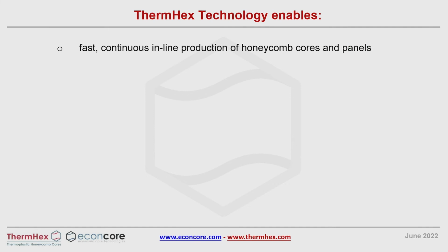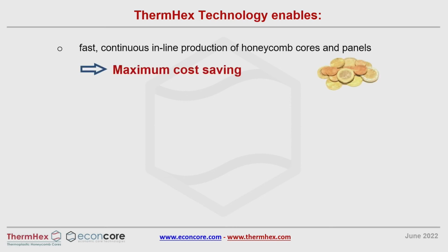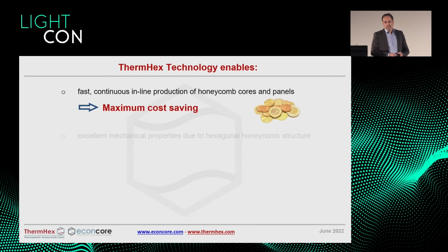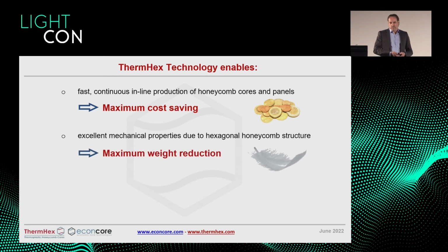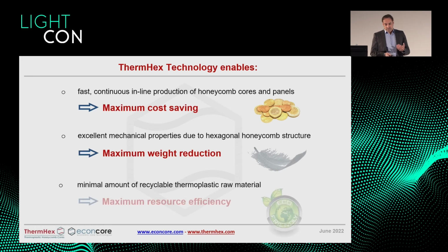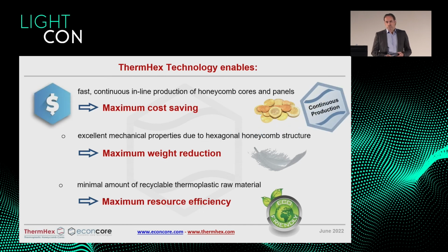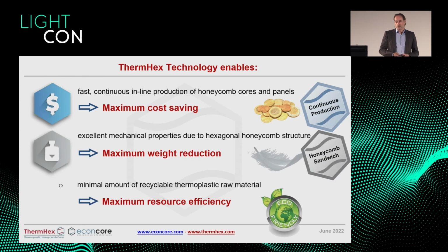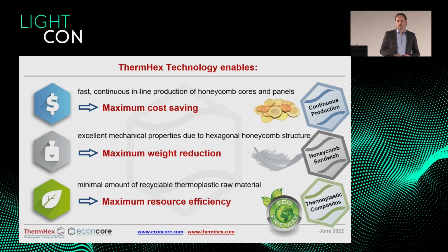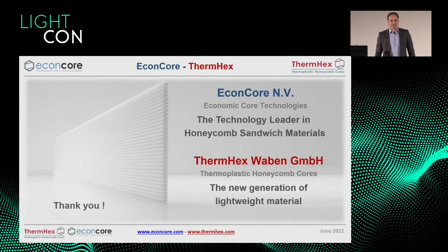So this brings me to the conclusion that we have with our process a fast inline production process for the cores and the panels, which allows maximum cost saving. We have the excellent mechanical properties of a hexagonal honeycomb structure, which allows maximum weight reduction. And we have recycled material, a minimum amount of material, and recyclable material, which is maximum resource efficiency. And this goes very well together because with a continuous production, we have a very cost-efficient way to produce those materials. We have, with the honeycomb sandwich, the weight reduction, and with thermoplastic composites, a very resource-efficient recyclable material. So with this, thank you very much.